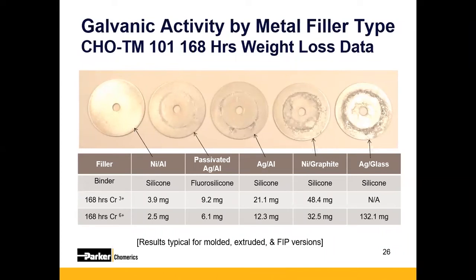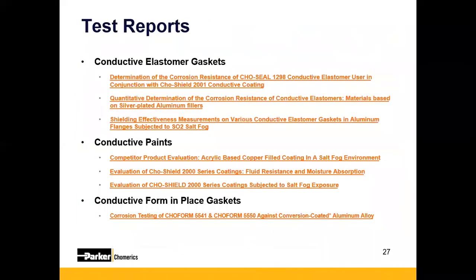So what you're showing me is that I'm probably not going to use a silver glass gasket in a very corrosive environment, huh? Exactly. So in this case, probably don't want to use the silver glass on a shipboard or an aerospace application. But it's important to note that there's a lot of great applications for silver glass in a Class A environment that don't see as much environmental exposure. And it's a low-cost material.